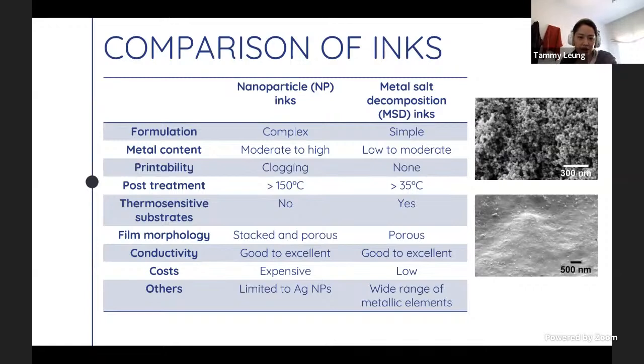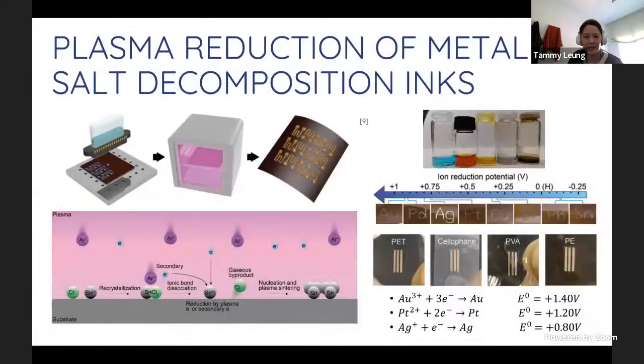Simultaneously, the cost of the ink is also greatly reduced, while there is an increase in the number of metallic films that can also be formed. Even amongst these improvements or changes, we see a similar conductivity in a range of good to excellent. And this only further shows that metal salt decomposition inks are superior to nanoparticle inks.